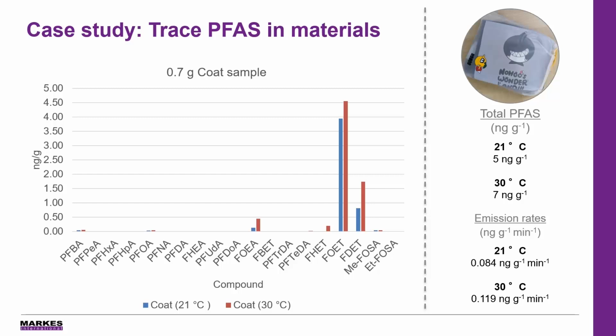And what we were looking for were the various different types of PFAS compounds. And you can see there at the bottom the ones that we managed to identify, and then we determined those as an emission rate, either a nanogram per gram, so an emission rate of mass of compound of interest per mass of sample that we were looking at, or as an emission rate, so looking at the nanogram of the concentration of the compound compared to the time that we were looking at there as well, so a nanogram per gram per minute emission rate.